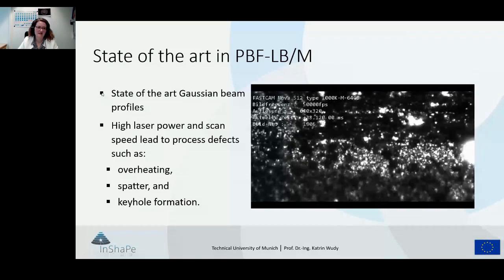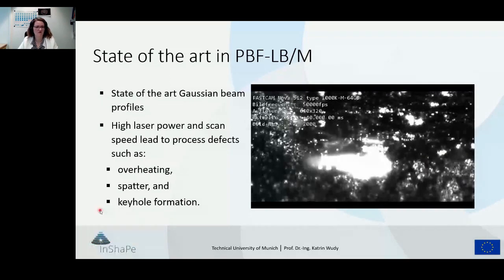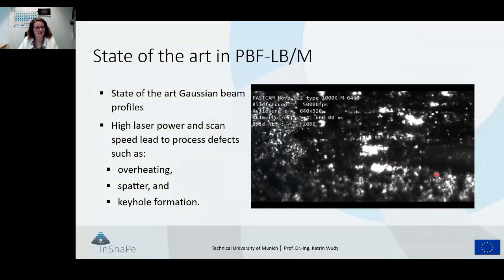The state of the art is that if you're using typical Gaussian beam profiles, which is again the video on the left-hand side, you have this really high energy input on one single point, which means you have really high thermal gradients. And these high thermal gradients on a really small scale may lead to overheating effects, to spatter formation, the mechanism we've seen before, or to keyhole formation. And the challenge if you have keyhole formation, instead of the transition between conduction welding and keyhole welding, is that you have quite a high probability of keyhole porosity. And this is, at the end, again a defect in our final component.